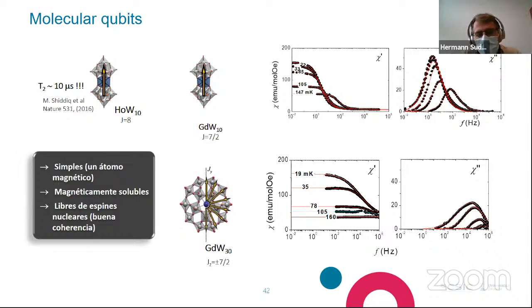Yes. Okay. And then what is the origin of chi double prime? What is the physical origin? Of the susceptibility, you mean? Of the imaginary part, yes. Yeah, this tells us that your system is absorbing energy here. It's like if you would perform a noise measurement, for instance, you will also obtain a peak, at the same position where the peak in the imaginary part appears.